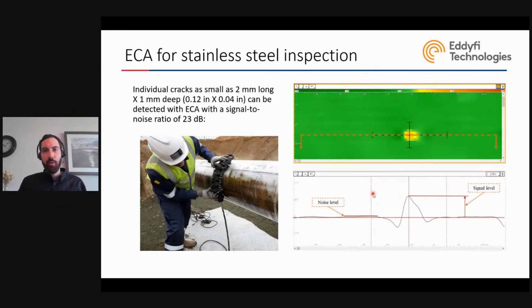So we pushed a little bit further and we went through different trials. And at some point, we were able to characterize the smallest external defect that we could find in stainless steel. And we basically put a number of around 2 millimeter long and 1 millimeter deep for this smallest flaw. And this is with a very high signal to noise ratio in a real life condition, in real life pipes. So of course, depending on the amount of corrosion, coating, surface roughness, surface condition, this number will change. We've done projects where we could find 1 millimeter long cracks, and some projects where it was more difficult because there was a thick coating on the pipes.